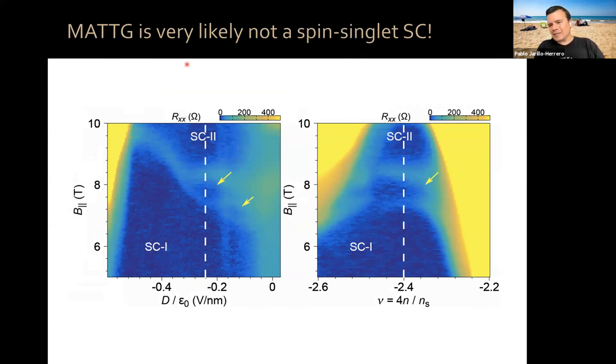Okay, so magic angle twisted trilayer graphene is very likely not a spin singlet superconductor. Okay, this high field phase is probably spin triplet, and the low field phase might be a linear combination of spin singlet and spin triplet, spin valley locked type superconductivity. So triplet components in addition to singlet components. It perhaps could also be triplet, although there are some theoretical reasons why the low field phase at zero field is unlikely to be just purely spin triplet, okay?